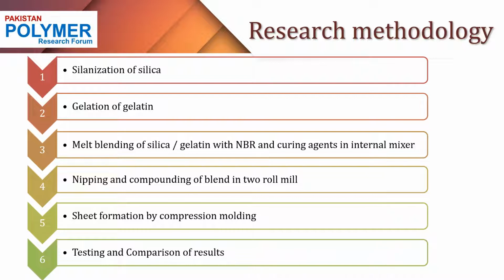The second step was the gelation of gelatin that was gelatinized in the presence of water under specific temperature and time conditions. The third step was the melt blending of this gelatin and silica with NBR rubber and a specific curing agent, as I have described above, the accelerators, the activators and the curing agent in the internal mixer. The fourth step was the proper compounding and mixing of this internal mixer blend in the two roller mill to have proper dispersion and distribution. The fifth step was the compression molding of this elastomer to make sheets to have specific samples for the testing purpose. And the last one was the testing and the comparison of the results.